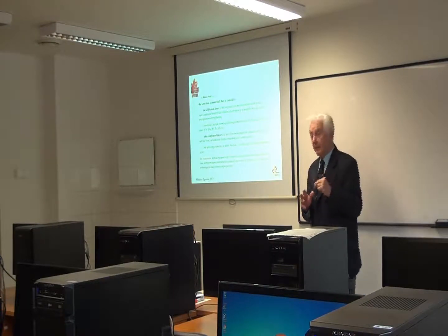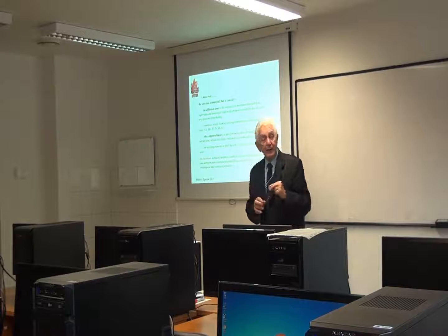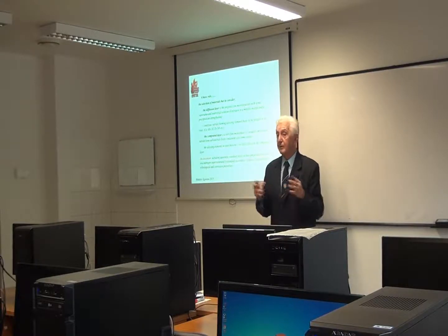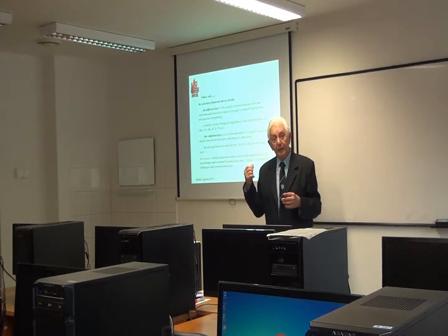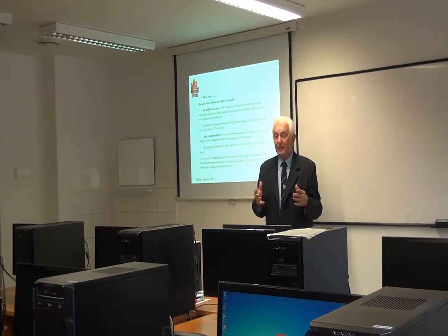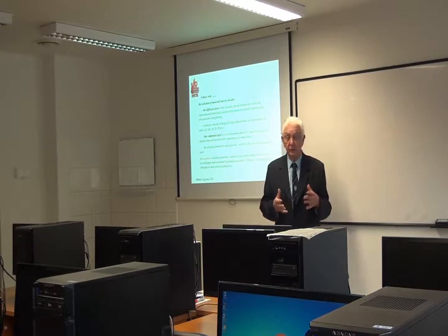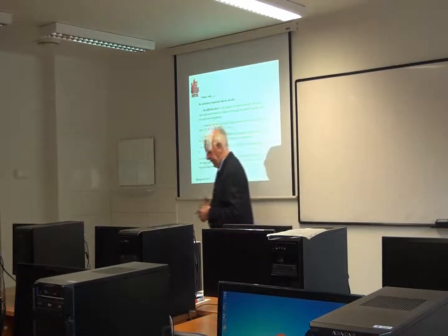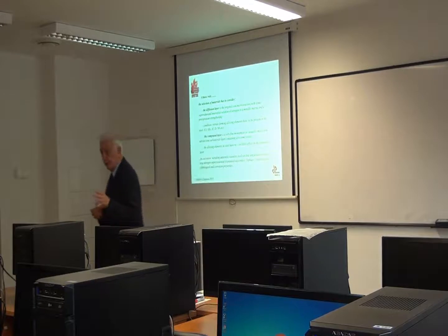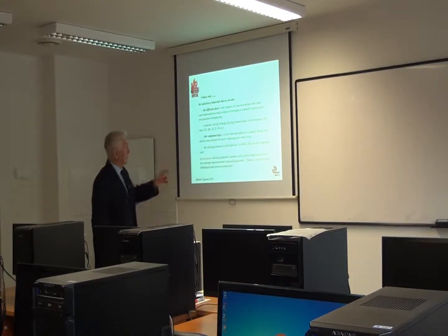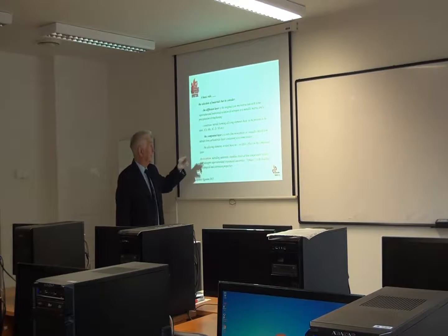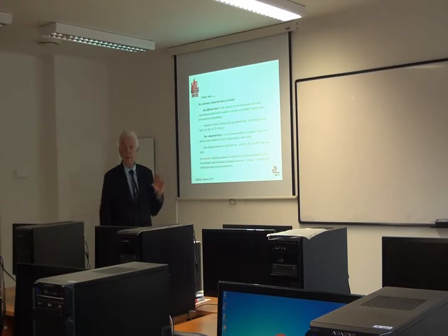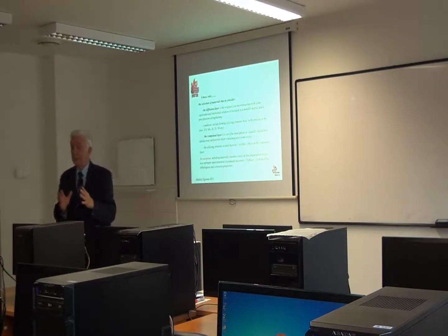This is why, whenever we have surface modification with such a compound layer, we used to say it is a ceramic conversion. This expression was also introduced by Tom Bell, and that is absolutely true, because the compound layer, due to the combination of iron nitrides and iron carbonitrides, has a completely ceramic character.